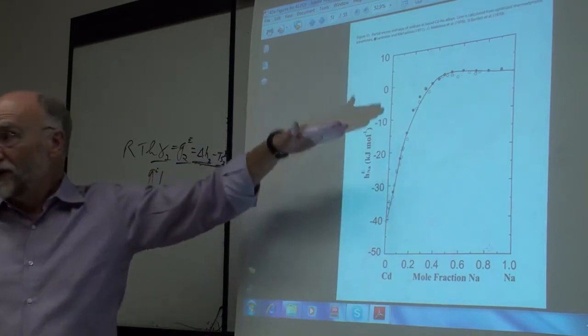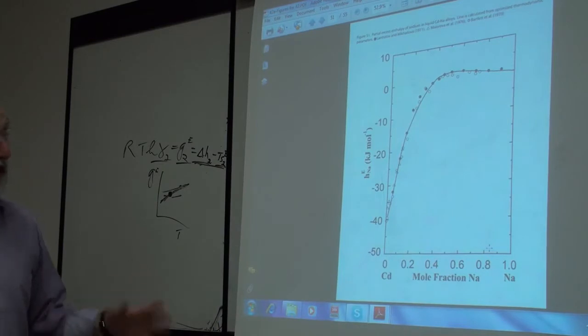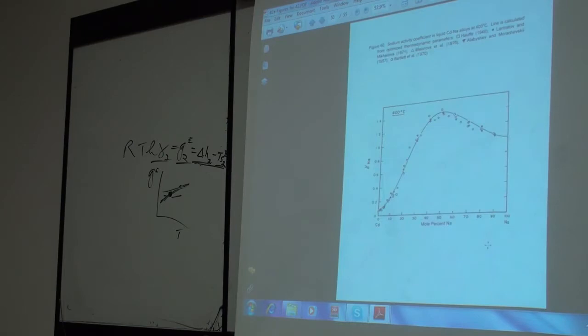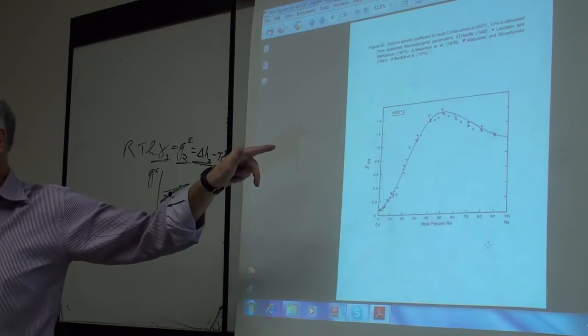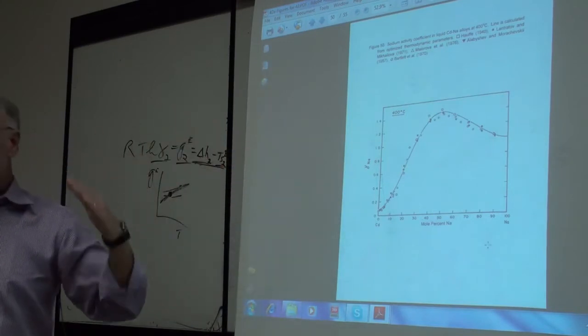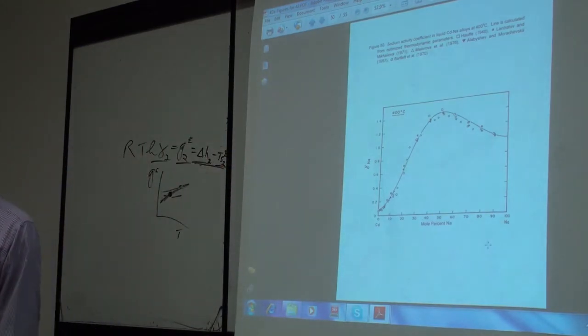These are the differences. What you really should do, if you're plotting this, is don't ever plot the HXS. Look at the log gamma at different temperatures and show how well each of those curves is fitted by your optimization. Because then you're looking at the actual data that were fitted. Don't plot derived data. Don't plot data that are taken from the slope, or that are derived, or that are taken from adding another. Just look at the actual data that have been measured.